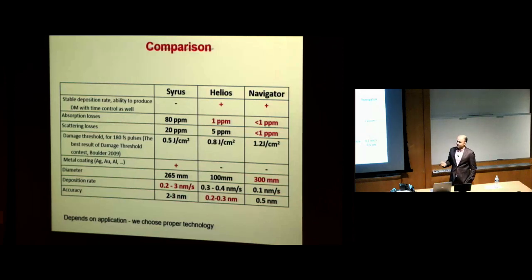The best thing about ion beam sputtering is that the layers are very smooth, which means our scattering losses are very low. This machine can provide very low scattering and absorption losses. That's the reason why this technology is used for all Galileo projects, for all gyroscopes, and everywhere you need very low total losses. The disadvantage of this machine is that it's very slow. When you try to deposit some thick coating, it takes 2-3 days to finish the coating. In comparison, the other machine does this in less than 10 hours.